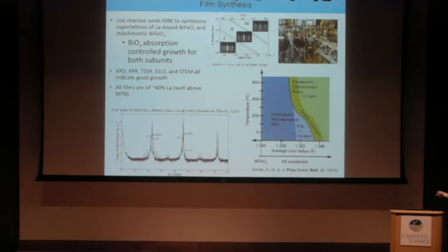You get a characteristic benchtop X-ray here, where our only contrast is the lanthanum on the bismuth site. That's the only Z contrast we have, and we still get nice, sharp superlattice reflections. This is for a 10-10 superlattice, 20 repeats. We get these nice superlattice reflections throughout the whole series, and they index correctly.